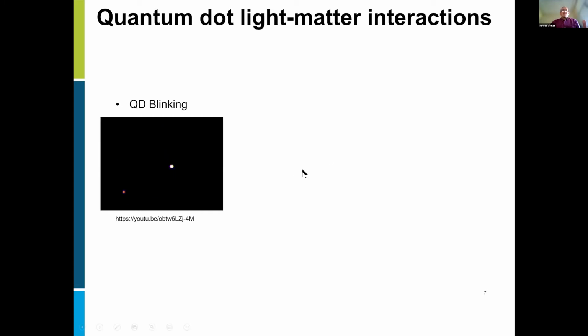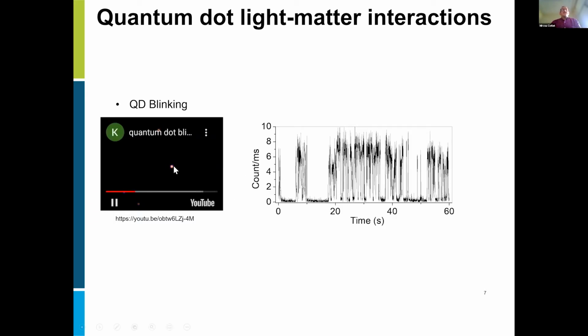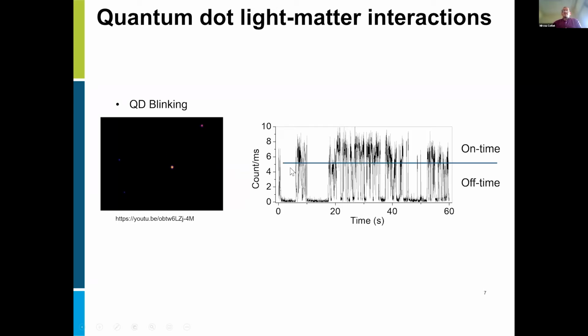Looking at this phenomenon, the blinking, if you look at a single particle and you monitor the emitted signal, in this case we call it luminescence or fluorescence, we see that in time this signal goes on and off, and occurs like bursts. So while one would expect that continuous irradiation should provide continuous emission for the single quantum dot, it's not the case here. And it's also noticeable that this on-off switching of the quantum dots is not a periodic function.